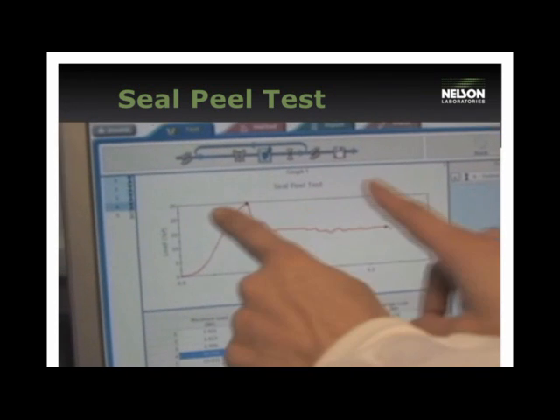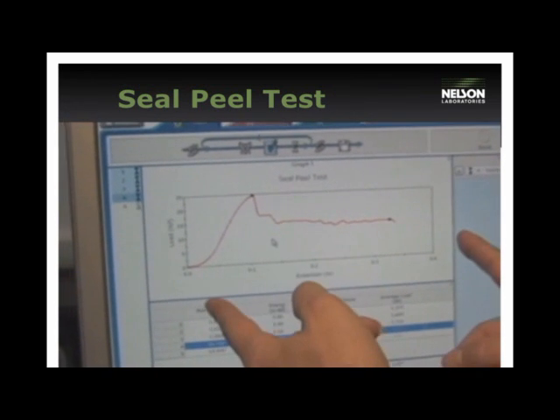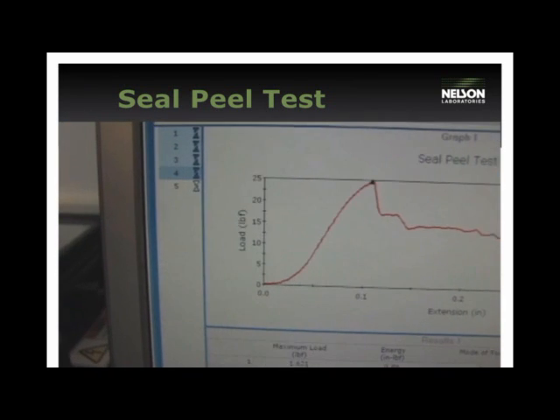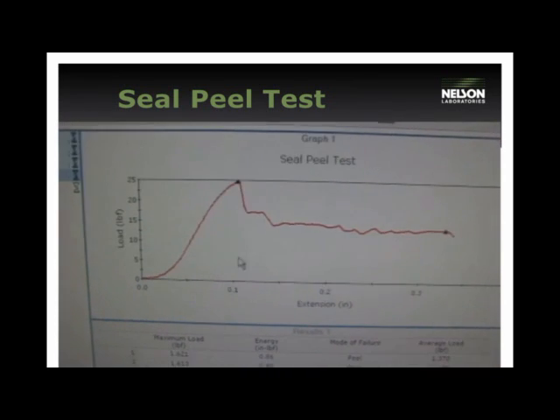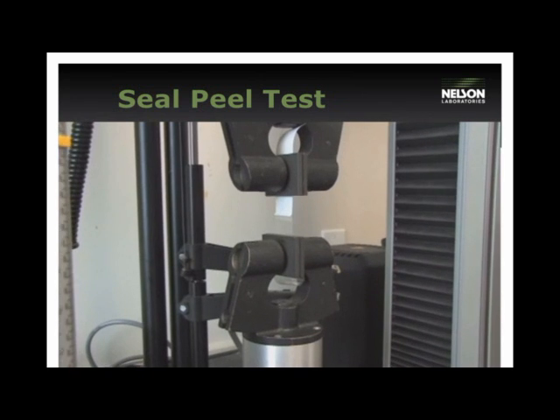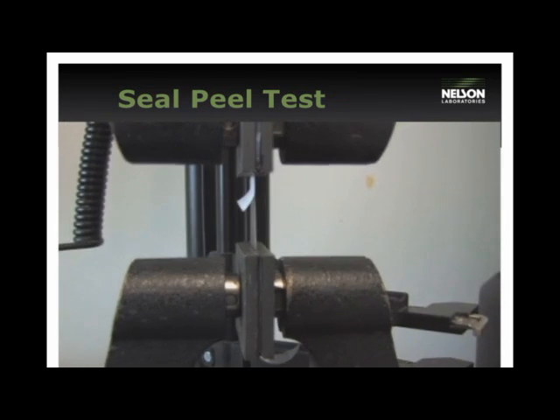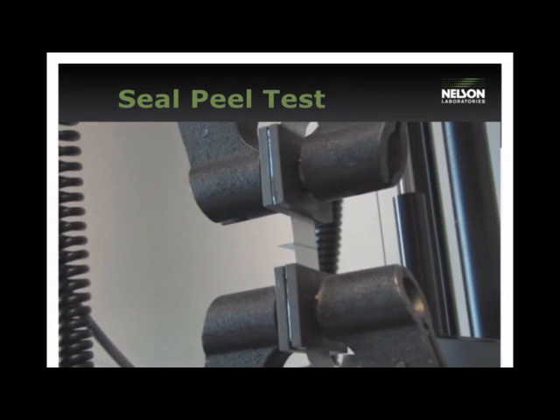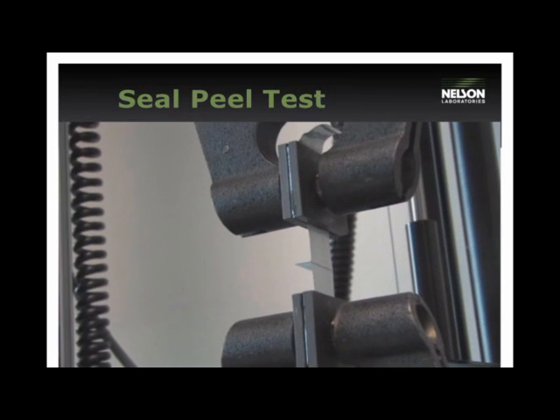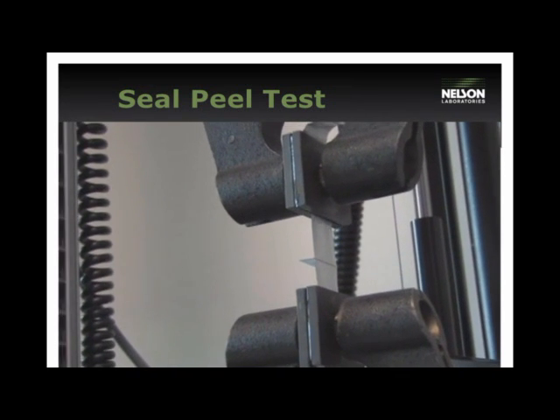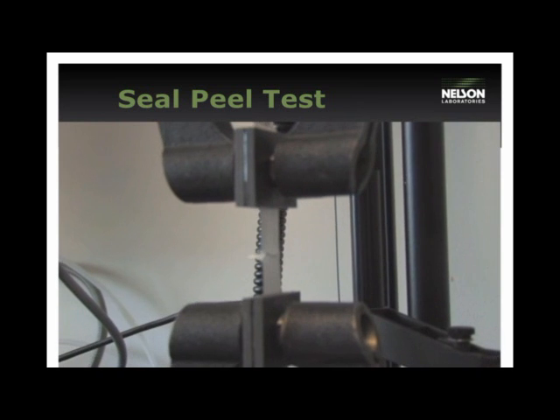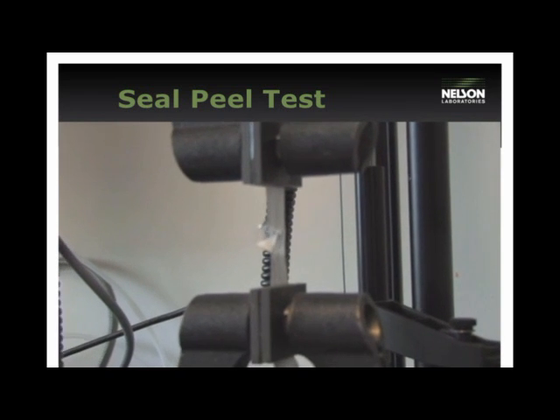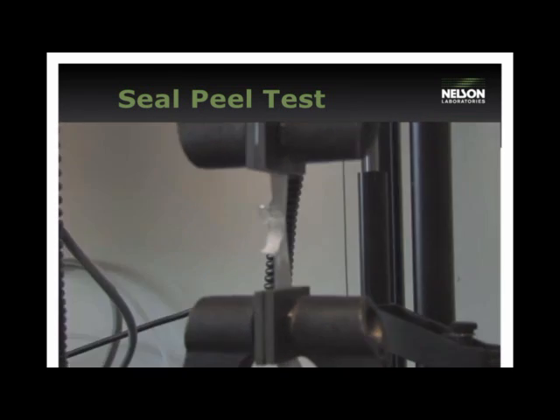When the curve is relatively flat, the computer can't calculate the average because it is looking for a certain number of peaks and valleys to average. Most samples will peel apart, and the mode of failure is reported as peel. When a sample stretches, it is reported as elongation. When the layers of a material split apart, it is reported as delamination.